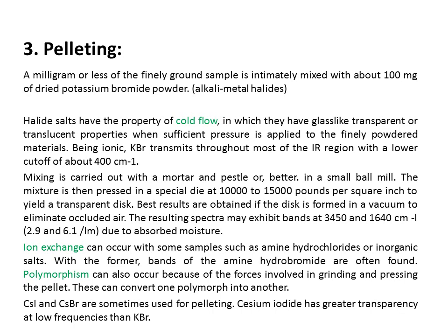The disadvantages of using this technique are that at high pressure, polymorphism could play a role. Your compound's one polymorph can change into another polymorph, or you can have some ion exchange reaction taking place. For example, if you have an amine hydrochloride and you mix it along with KBr, bromide can easily displace your chloride, and naturally your analyte will now turn out to be amine bromide, correct? So that's the problem. Ion exchange reaction or polymorphism could be the problem when you use the pelleting technique.